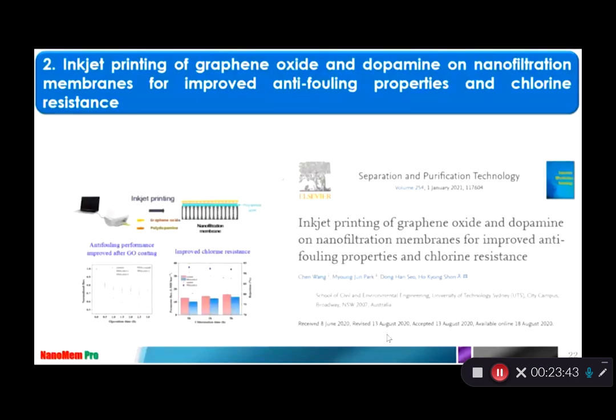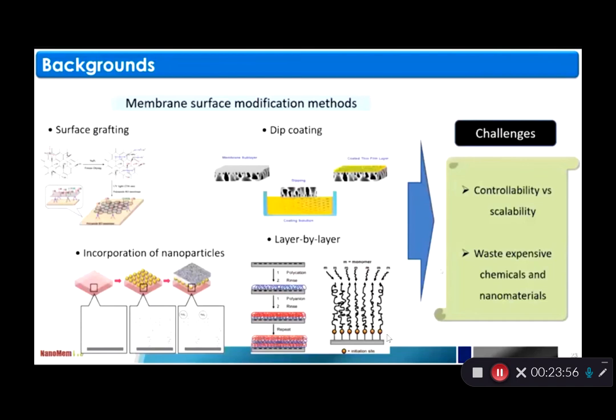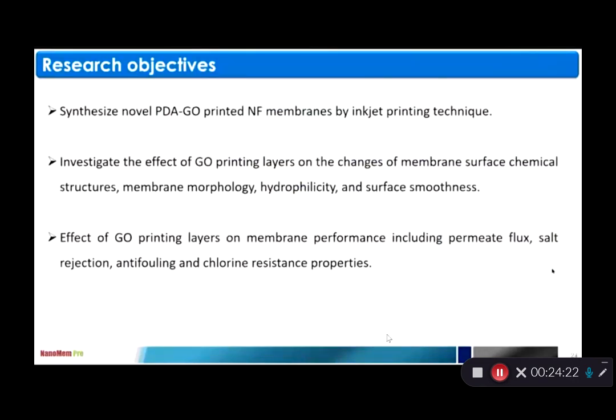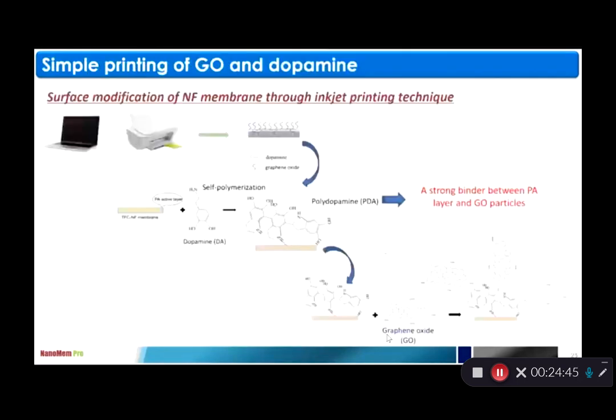So we try to see how we can make an anti-fouling and chlorine resistant membrane using graphene oxide coating with this inkjet printing. So this is the background. In general, people try surface grafting, coating, and incorporation of nanoparticles layer by layer. And the challenges are controllability versus scalability, and the waste of expensive chemicals and nanomaterials. So we synthesized a novel PDA GO printed nanofiltration membrane for wastewater, and investigated the effect of the GO printed layers on membrane performance in terms of permeate flux, salt rejection, as well as anti-fouling and chlorine resistant properties.